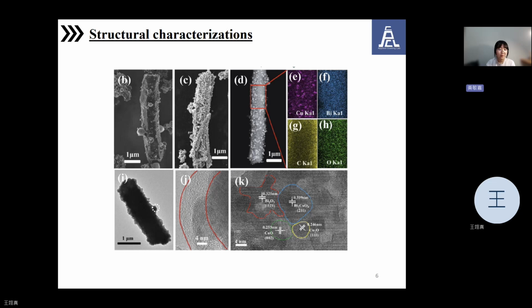The HRTEM reveals well-defined lattice fringes. This represents the atomic layers inside the crystal. Each fringe corresponds to a specific spacing between the planes of atoms. These fringes help identify the crystal structure and confirm the crystallinity of the material.